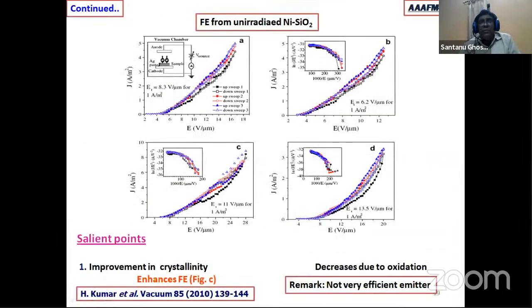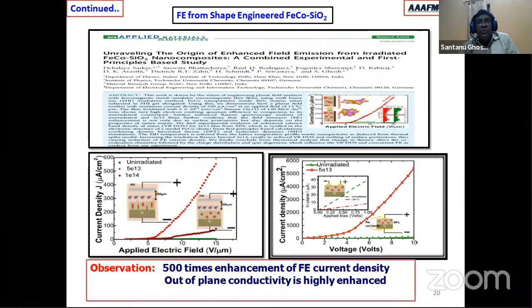Now with this embedded metal nanoparticle, when we did a field emission measurement, we could observe field emission current. However, the field emission current density is quite low, and definitely is not something which one can use as a field emission electron source. After that, we used those shape engineered metal nanoparticles. Now you can observe that this green line shows the current density of the particles which are spherical, not shape engineered, and this is a current density which is almost 500 times higher for the particles which are of elongated shape. So there is a huge enhancement in the current density, and this can be tuned by changing the fluence.